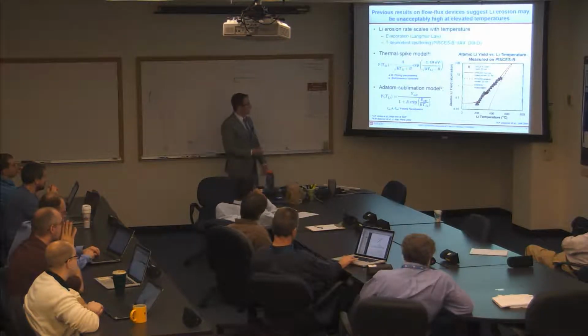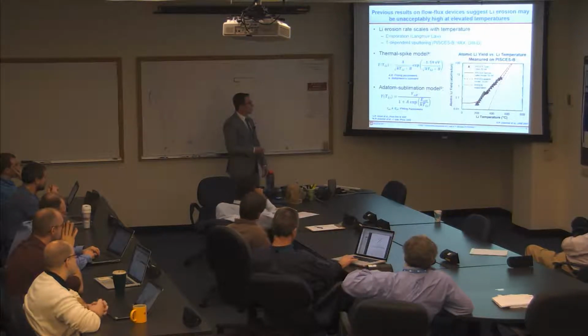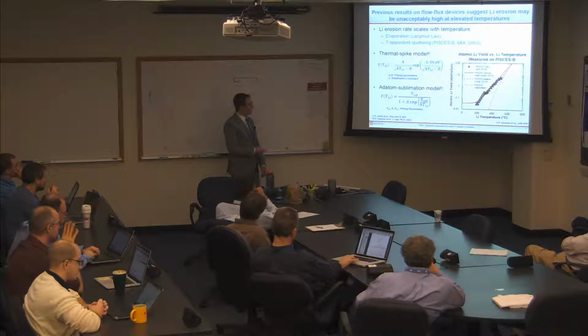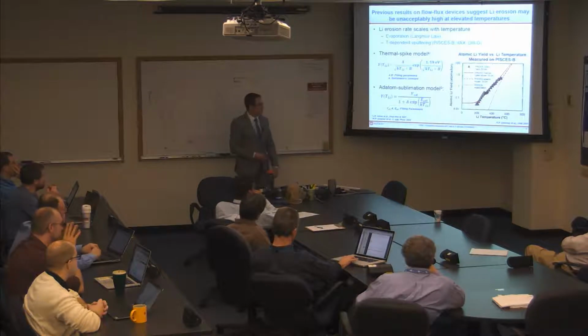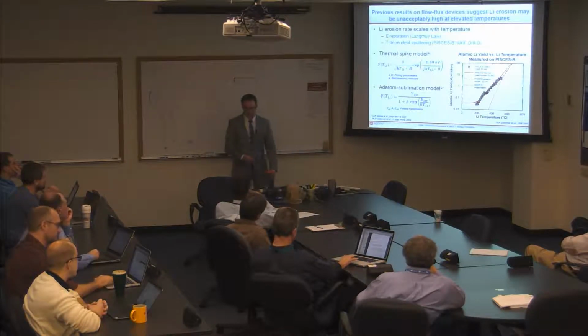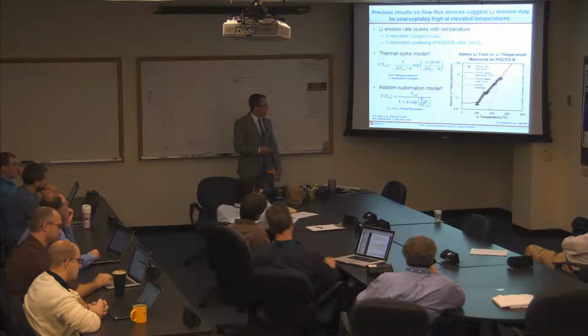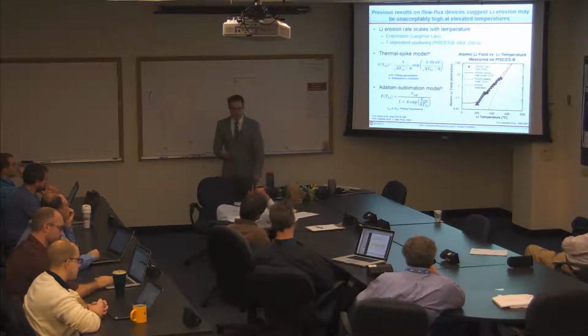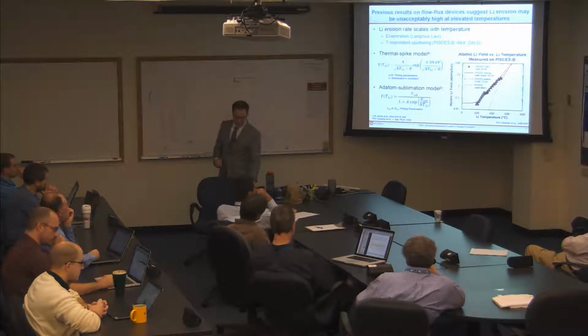But just see that the temperature-dependent erosion rate, which is given by Y, this yield, is expected to scale exponentially with temperature. And the scalings for these are a little bit different for the thermal spike model and the adatom sublimation model. But they both increase exponentially with temperature, which provides very pessimistic estimates of what temperature you can reach with a lithium plasma-facing component.